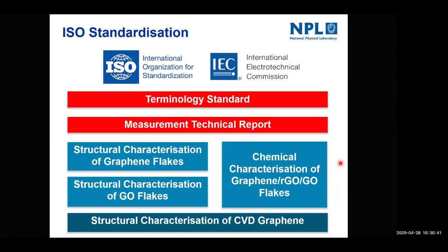So going back to the landscape that we looked at earlier, we've really here talked about the structural characterization of graphene flakes. Now, if we look at graphene oxide, the SEM and AFM is applicable there as well in the same way. And if we look at the structural characterization of CVD-grown graphene, the standard here is actually using Raman and TEM. Now, not in exactly the same way as I've described here, but it's using those techniques and the fundamentals of those techniques to allow the understanding of the number of layers and coverage of CVD graphene on a substrate. But again, I mentioned before, chemical properties are really important as well. If you look at things such as composites, many different application areas, the chemistry, the surface chemistry particularly, will play a really important role in how well the material improves your product.